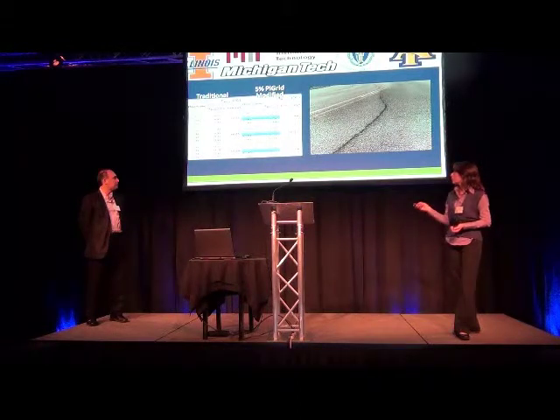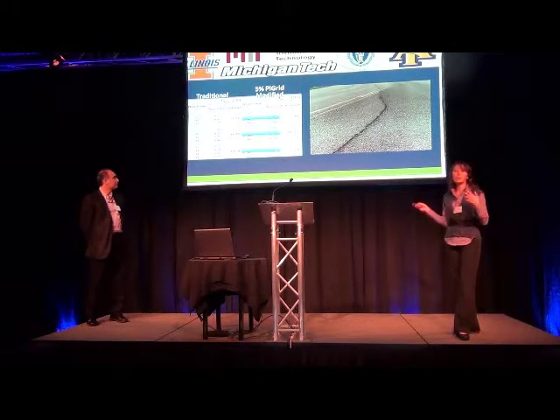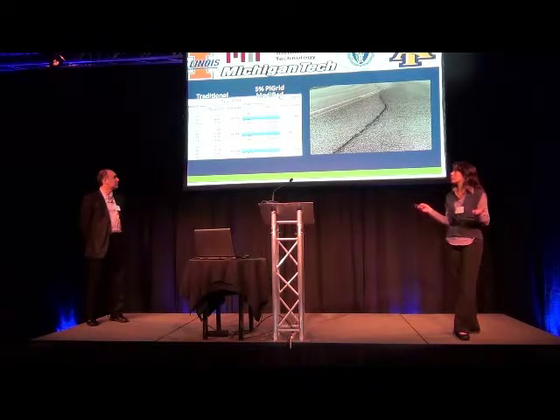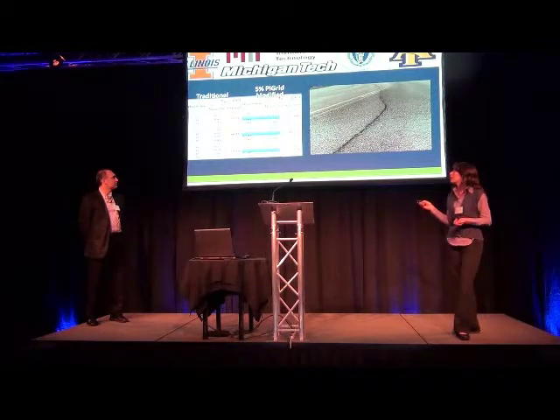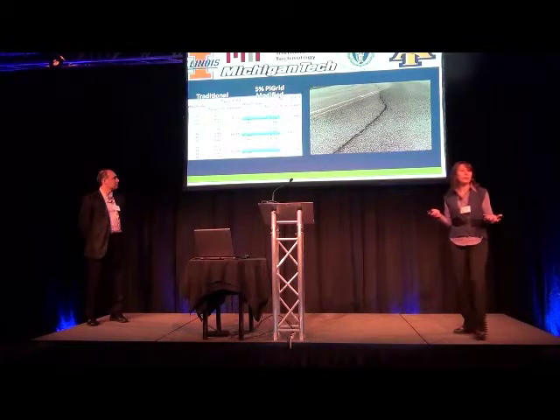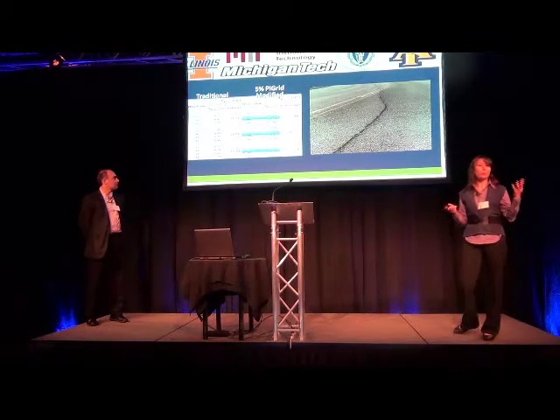So we started using the recycled material here. This is 15% recycled material. And as you can see, the cracking temperature will be reduced in the conventional. But we added our adhesive, and now we are up to -20. Of course, it's a reduction from the control to 15%. And then we said, okay, if we are improving this cracking resistance, can we push the envelope even further?